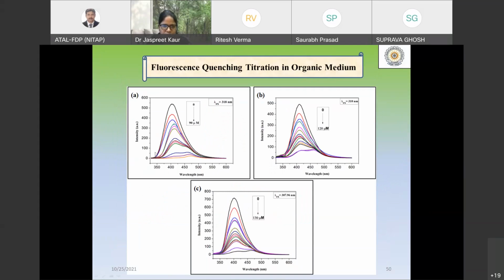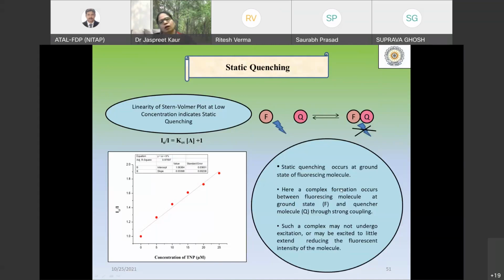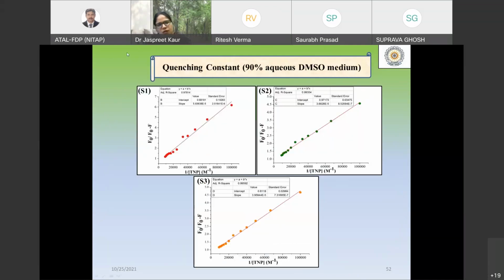So this is the fluorescence quenching titration in the organic medium, DMSO. You can see. Now in this particular case, these triaryl imidazoles show static quenching. If we see the Stern-Volmer plot, you can see they show linear behavior at low concentration. Apart from that, lifetime studies also show that this KSV is constant, and that is why it shows static quenching, not dynamic quenching. So this is the quenching at 90% water and 10% DMSO medium. You can see that it shows linear behavior in the plots.